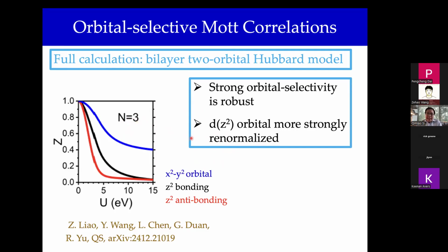And so this is a physical filling case for the bilayer nickelate. And the renormalization factor, Z, is the quasi-particle weight. At U equals 0, in the non-interacting limit, Z equals 1. And in the relevant interaction range, we show the result of the renormalization factor for the 3dx square minus y square orbitals, 3dz square orbitals in the bonding combination, and 3dz square orbitals in the anti-bonding combination.